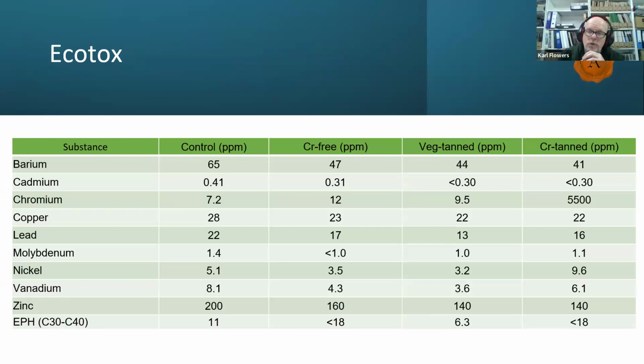You can see the controls on the second to left column, the chromium-free in the middle, vegetable tanned and chrome tanned, detection of ecotoxins on the right-hand side. Very clean sheet, nothing to be concerned over here. The control levels were not largely different from the chrome-free, veg tanned and chrome tanned leather, except for the presence of chromium. And you can see that we had at least 5,500 parts per million of chromium in these composts as a result of chrome tanned leathers being broken down.